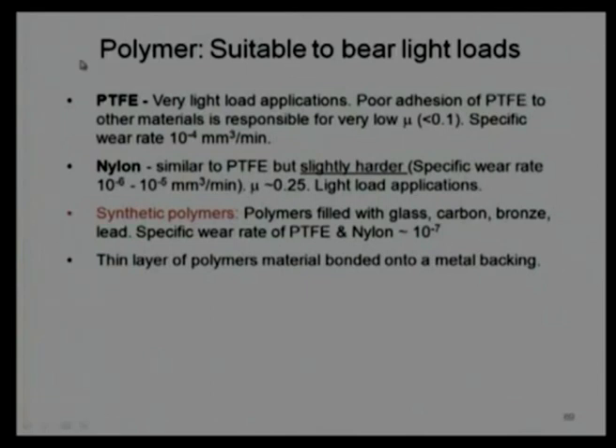When we want to reduce the wear rate, often we choose nylon. Nylon is one of the most commonly used materials in most toys, where nylon bushes are used, or wherever slightly higher hardness and slightly higher life are required compared to this kind of wear rate. Obviously, if a lesser wear rate is required, then we can use nylon. Also easily available in the open market. However, the only disadvantage of nylon in place of PTFE is a high coefficient of friction. The coefficient of friction is 0.25. That means we lose almost 2.5 times more energy compared to PTFE. Again, we are using the word, they need to be utilized only for light load applications. Their specific wear rate is lower by 10 to 100 times compared to PTFE. However, PTFE has a major advantage of the coefficient of friction, and we do not want to lose it.